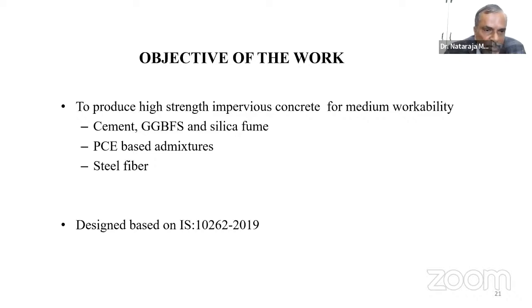And also we have the PCE based admixture, polycarboxylic ether based admixtures. It is a new generation admixture, works on the principle of steric hindrance. It's not working on the principle of electrostatic repulsion. Electrostatic repulsion is a concept generally observed in plasticizers. And today we have high molecular weight polycarboxylic ethers and esters with the steric hindrance concept, wherein about 0.25%